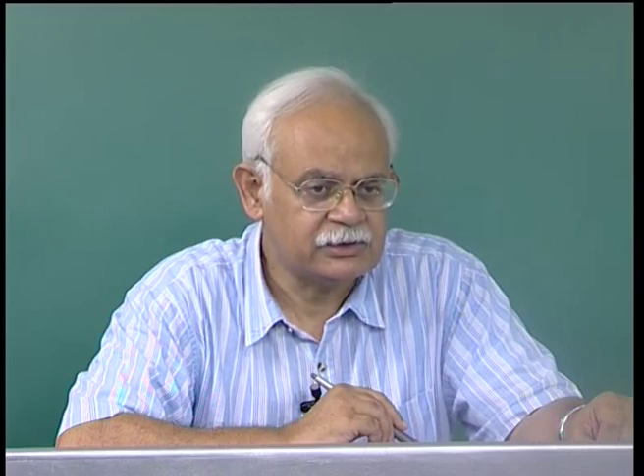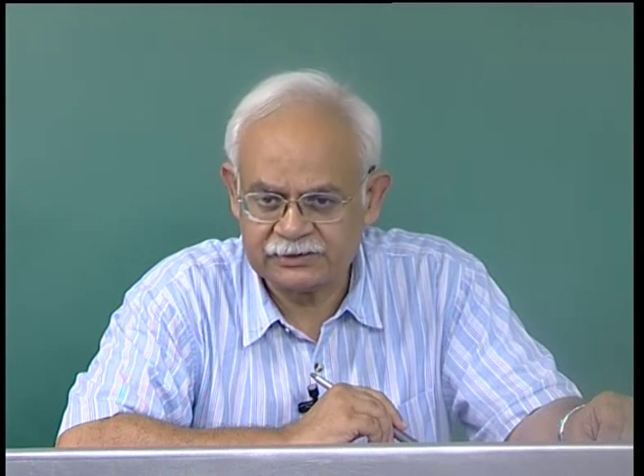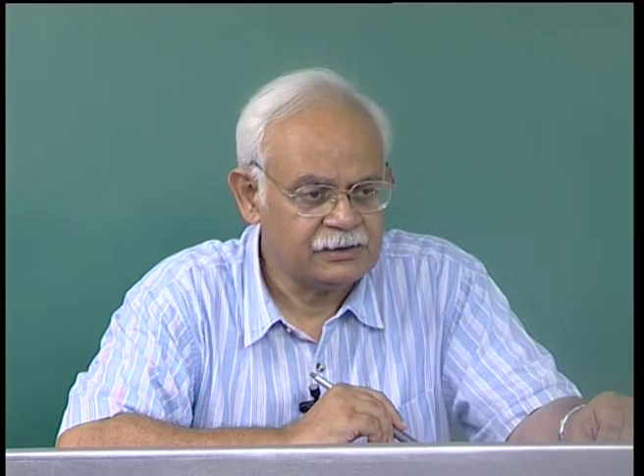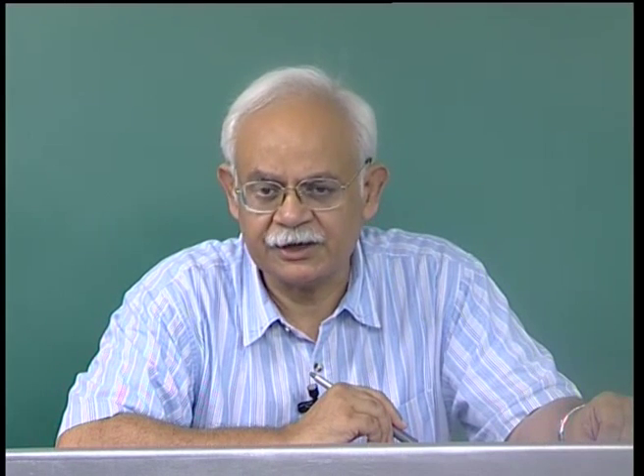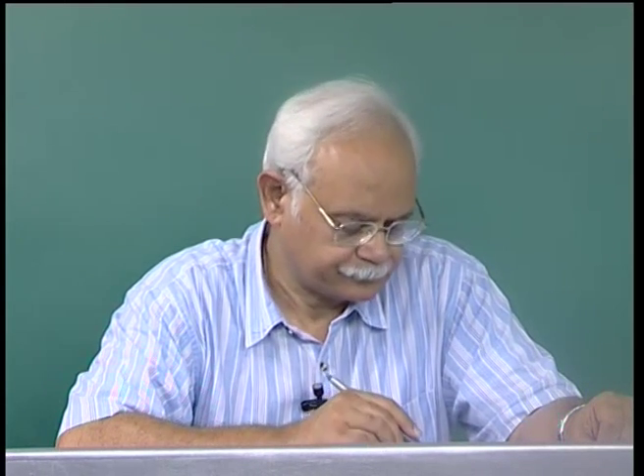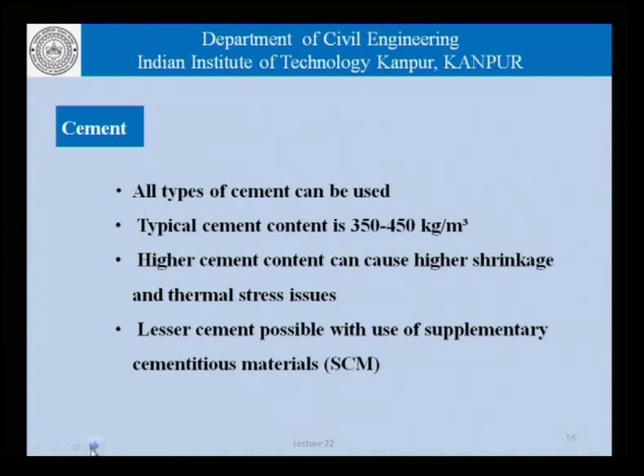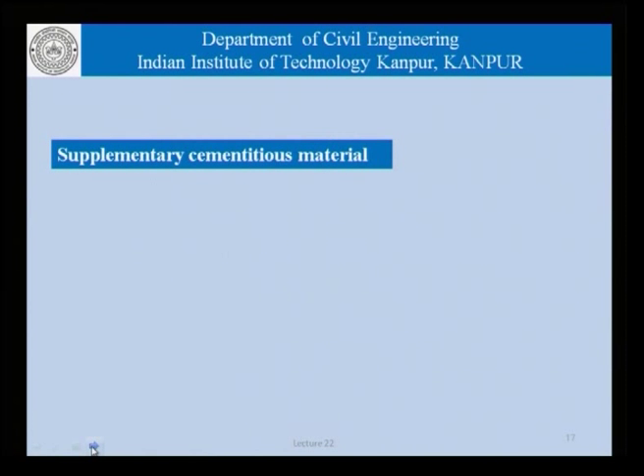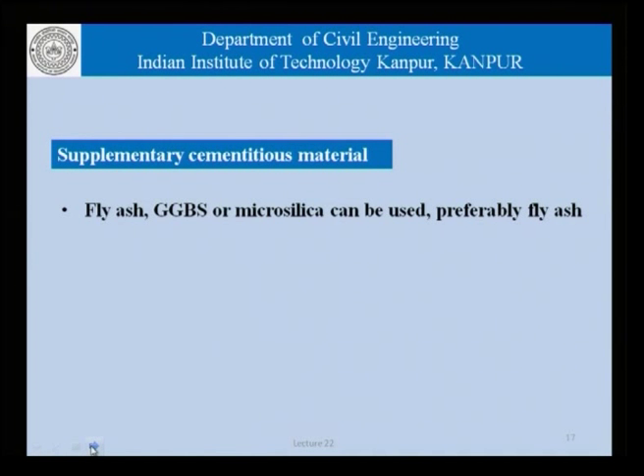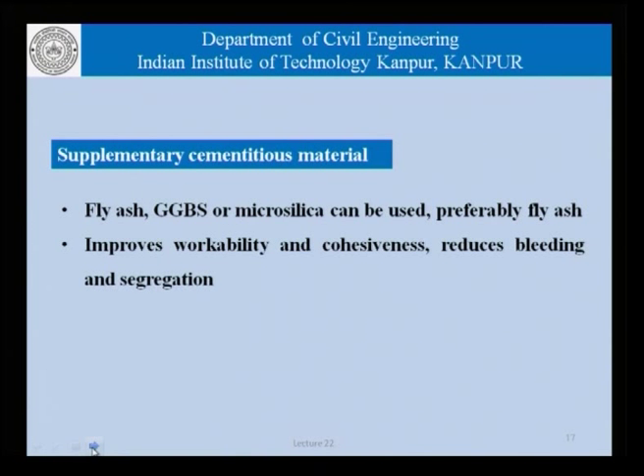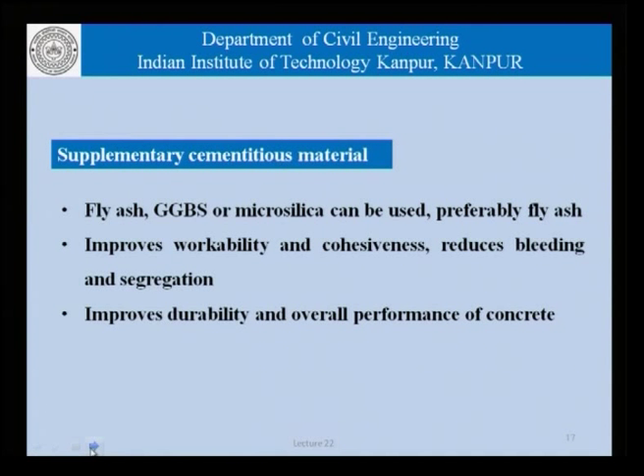We would rather use materials of similar fineness, but not having the hydration related issues in terms of heat and so on. And as we have stated, lesser cement content is possible by the use of these supplementary cementitious materials. We could use fly ash, blast furnace slag or micro silica, preferably fly ash because of its spherical nature. Their use improves the workability and cohesiveness, reduces bleeding and segregation, improves durability and overall performance of the concrete.